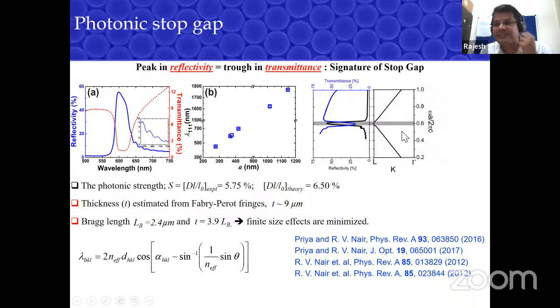And we calculated the band structure, the dispersion relation, and you can see that it compares nicely with our experiments. So indeed, we have a nice result, and our system actually shows a band gap for light. And this is angle dependent, polarization dependent, and it gives very interesting light matter interactions, which I'm not discussing today, but probably you can look at this paper if somebody's interested, and we published quite a series of papers on these things.